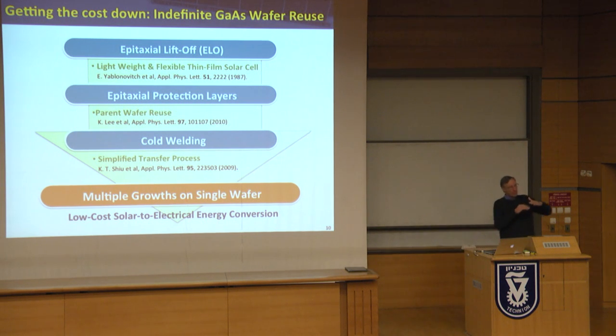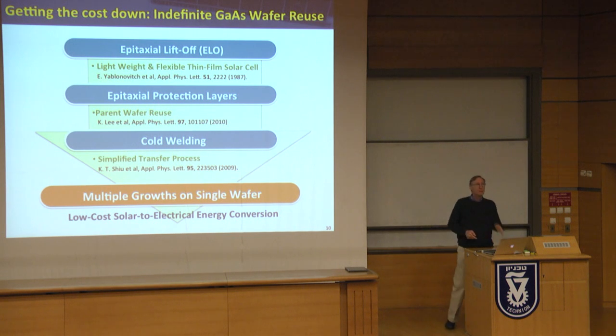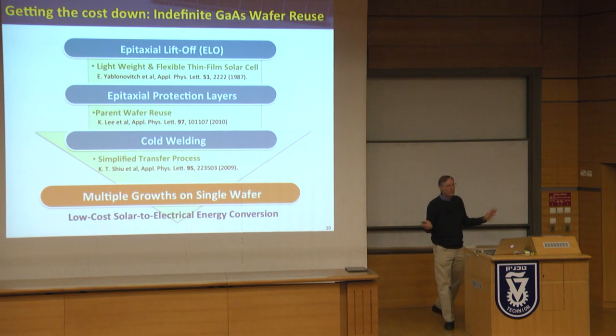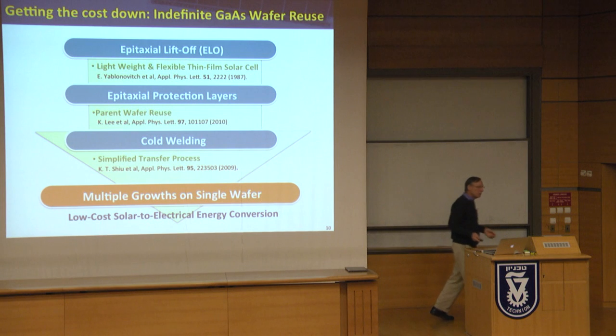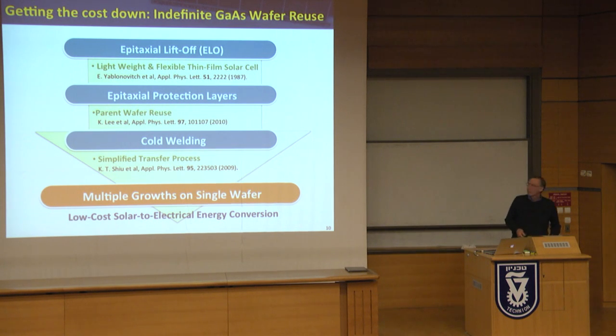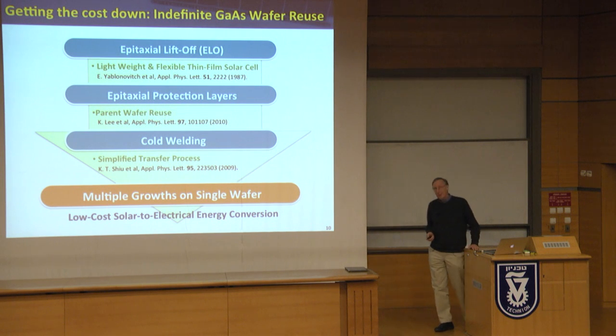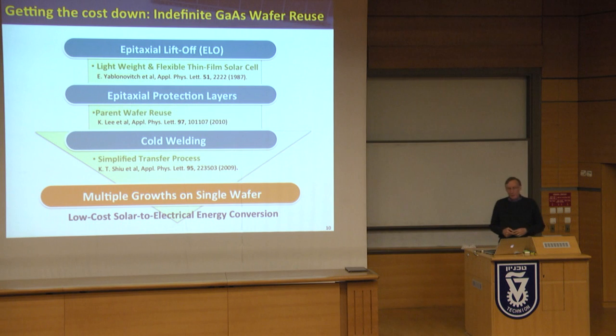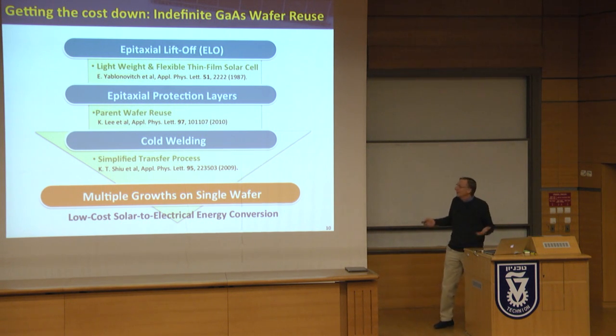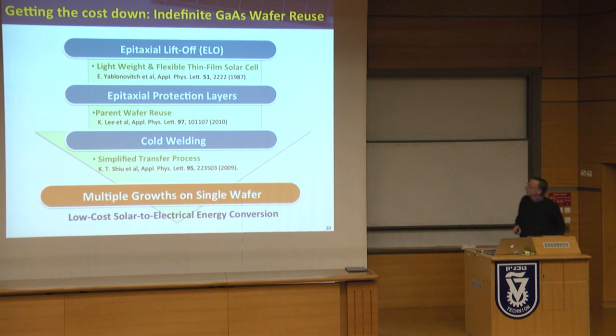The problem is that when you etch away that sacrificial layer, you leave damage on the substrate. And so you have to polish the substrate. Once you have to polish the substrate, you can use the substrate maybe 3 or 4 times and you're done, if you can do it that many times. I think the limit of that process has been about 5 with polishing. At $20,000 per square meter, you're now down to what, $4,000 per square meter. It's not a big jump.